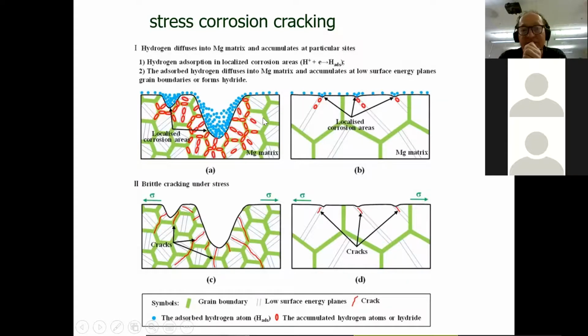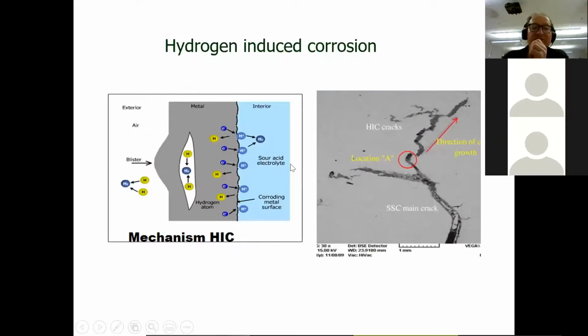And this is in magnesium. This is magnesium matrix. It's a magnesium alloy. So magnesium also suffers from this problem. And magnesium reacts with hydrogen to form hydrides. So therefore, magnesium is particularly susceptible to stress corrosion cracking because it very easily reacts with hydrogen. And so therefore, we talk about hydrogen-induced corrosion. So HIC for short. So we have two acronyms. We have SCC, which is stress corrosion cracking, and we have HIC, which is hydrogen-induced corrosion. And the two things are related, as I've just said. One actually causes the other. The hydrogen embrittlement, or the hydrogen-induced corrosion, causes the stress corrosion cracking to occur.